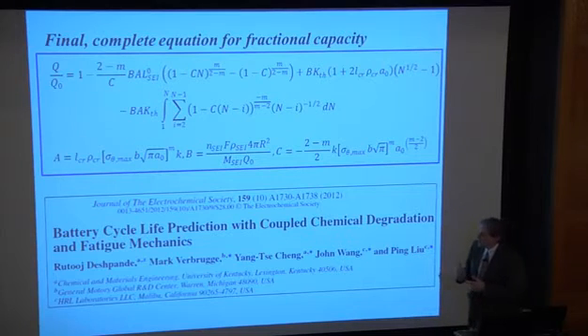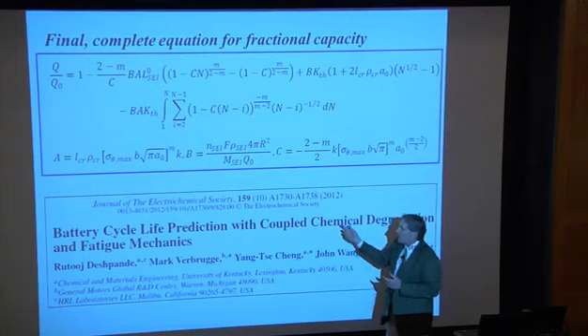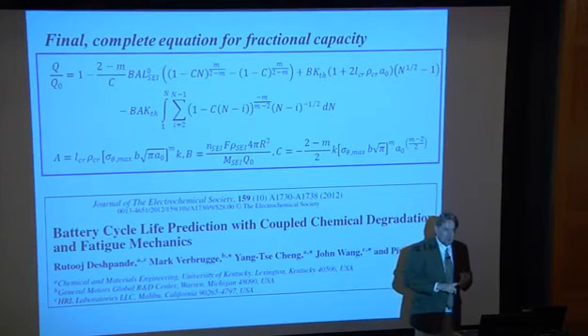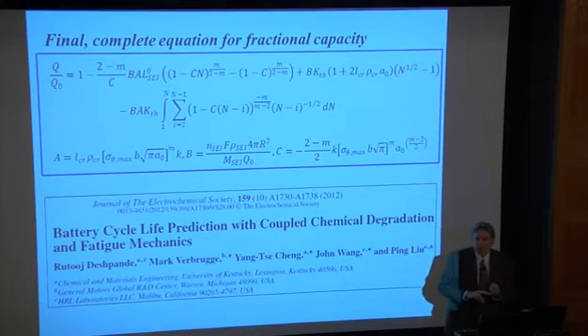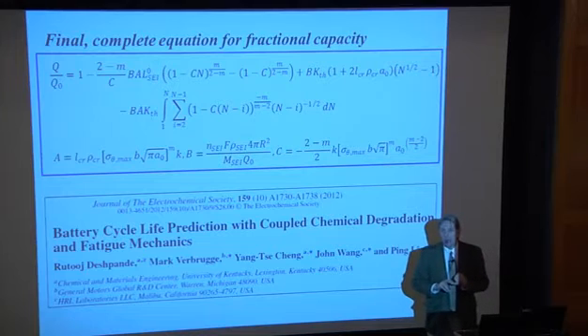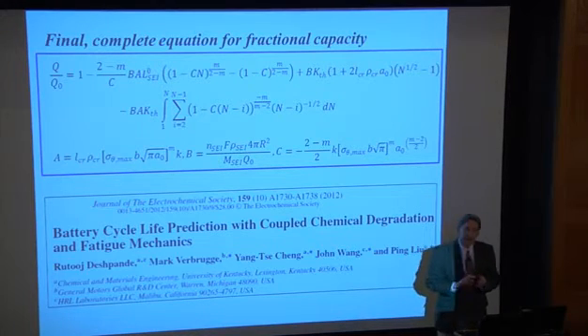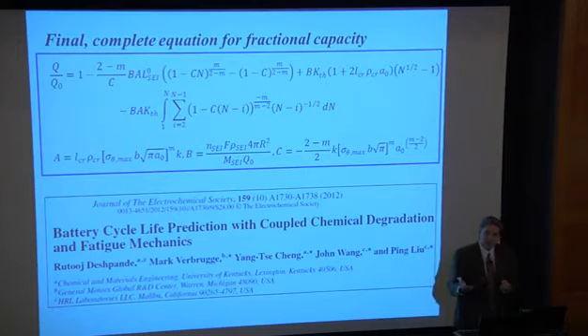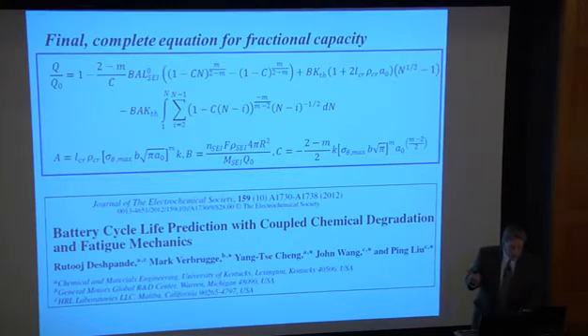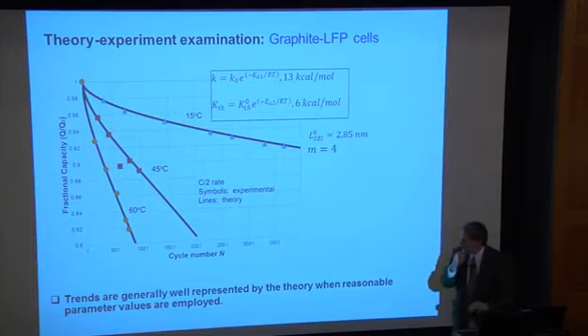My feeling is that there wasn't a previous publication before this one that coupled something like Paris law or some other method for a crack growth, crack propagation model, and then diffusion-induced stress, so you're solving your transport equations for lithium solute inside of the host material, and then the chemical degradation that occurs at the surface, so those chemical kinetics. Those are combined in this model to try to map out the life characteristics.